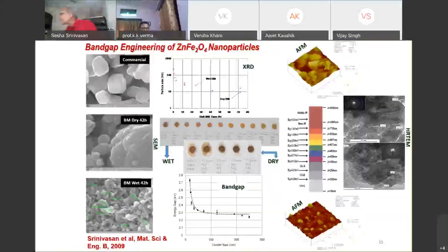The second thing is on the band gap, because as solid state physicists and material chemistry people, adjusting the band gap is a huge challenge. How can you adjust your bulk property through band gap engineering so that you can shift the electromagnetic spectrum? You can go either to the blue shift or the anomalous red shift. By adjusting the band gap, you change the wavelength. So this is again a project where we use a bulk commercial zinc iron oxide and ball mill it for up to 72 hours.